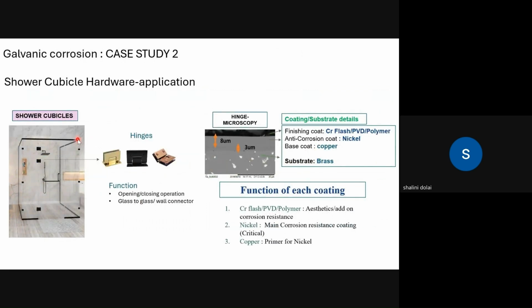And another case was the shower cubicle. In shower cubicles, we have hinges like this. They are usually coated with nickel and chrome, and the base is made of brass. Here we have brass, we have nickel, and then this top layer, this 8 micron layer is nickel, this is copper, and very thin, we cannot see it in the microscope, but there is a chromium layer.